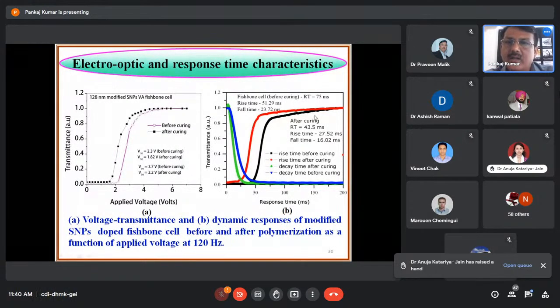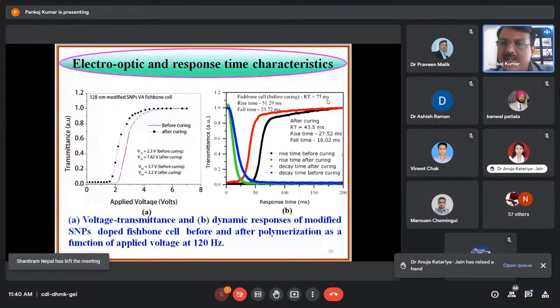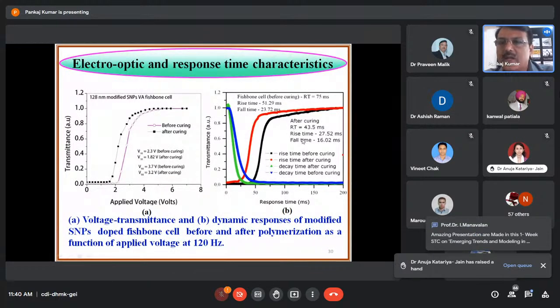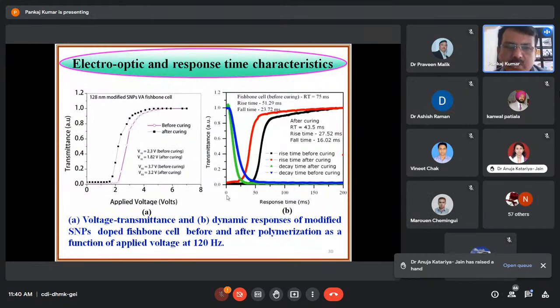Again, you can see here the response time after curing, and before curing the response time. Here before curing the response time is 75 millisecond, rise time and fall time are 51 and 23 millisecond. After curing the rise time is 43.5 millisecond, means response time. Rise time is 27 and fall time is 16. So voltage transmittance and dynamic response of modified silicon nanoparticle doped fishbone cell before and after polymerization indicates that if